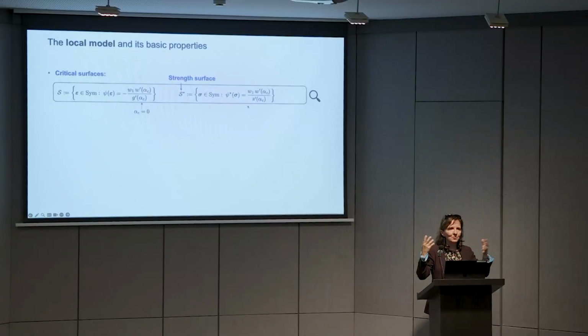And so this allows us to interpret the boundary of our admissible stress domain as the strength surface of the material. So essentially the strength criterion of the material. You may know about strength criteria because, I mean, anybody doing work in damage has this notion of when a material fails. So in the multi-axial stress space, you have typically some surfaces that tell you when the material fails in a way, no? What are the stress combinations that cannot be overcome? And this is essentially what we have here, the strength surface, if we put alpha C here.